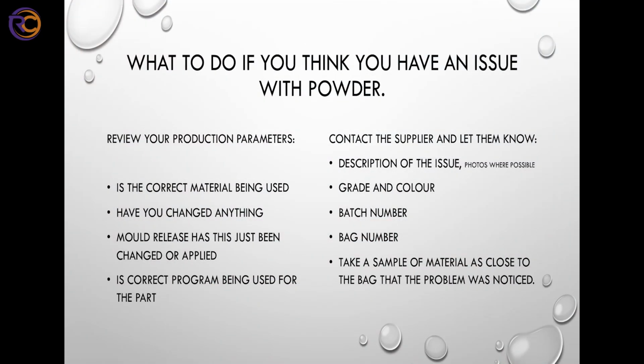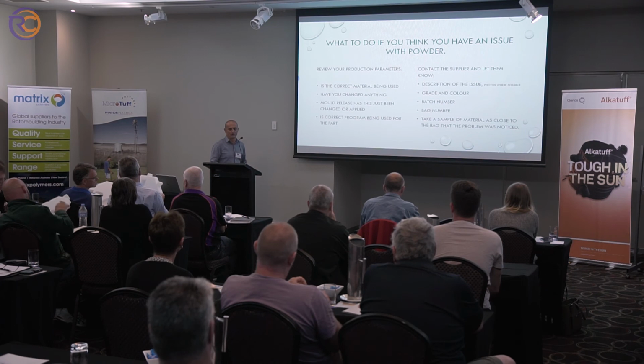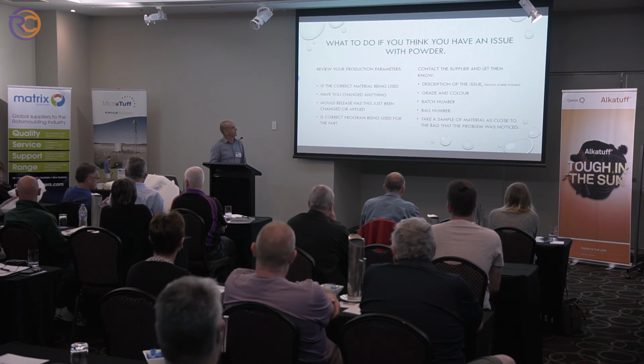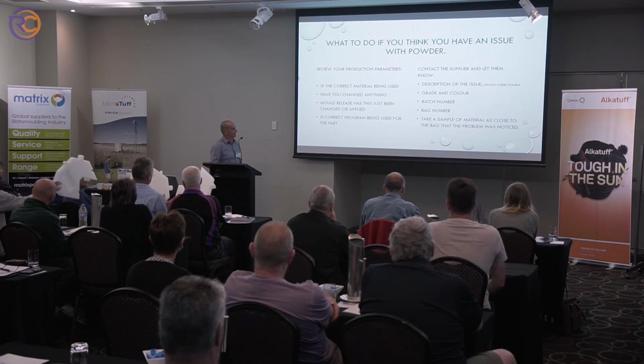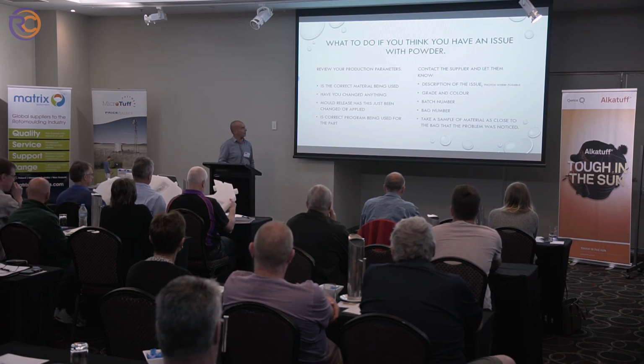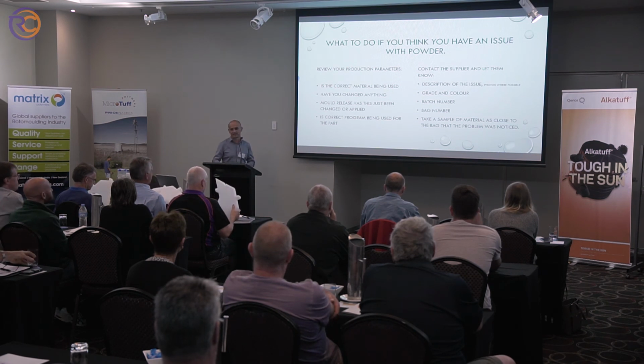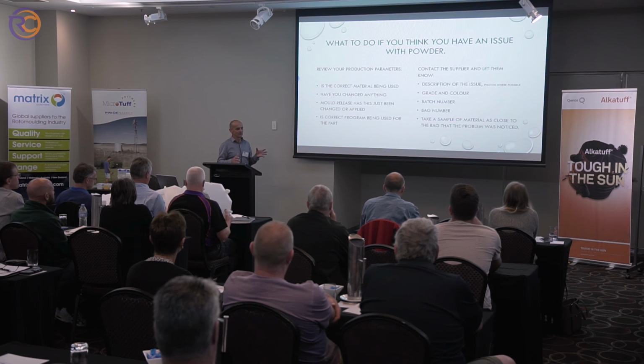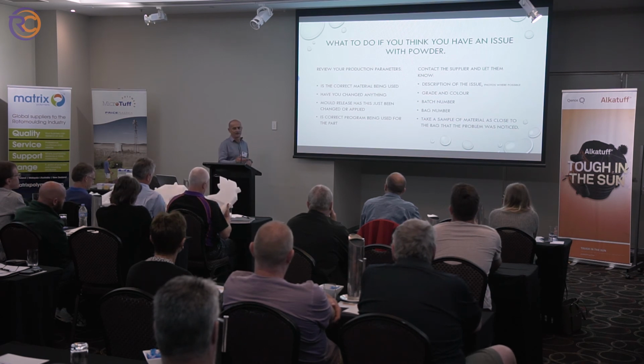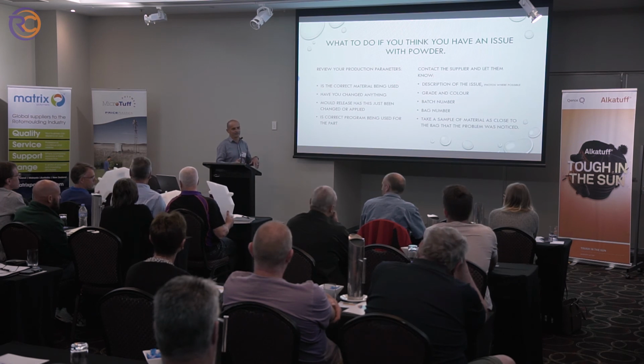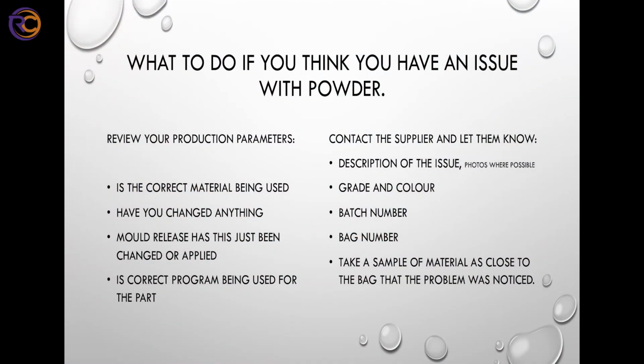So, now what happens if you do have some problems? Well, the first thing is, if you've got some moulding problems and you think it's related to the powder, review your production parameters. One of the things is, is the correct material being used? As I explained, you'll see in the samples, you can have some natural material and you'll be moulding a 5 melt flow, and then your operator throws in a 3 melt flow, and it's going to mould completely differently. And have you changed anything? I mean, 90% of the time, customers do ring us and say, look, we've got a problem with your powder, but 90% of the time, it's actually some other factors.